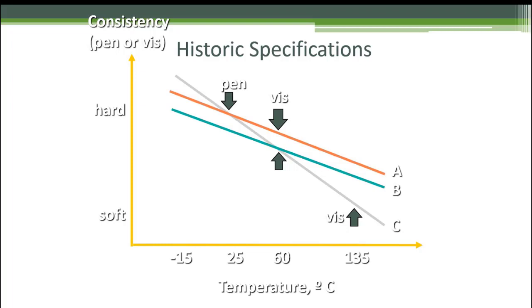But same traffic, same roadway, what happens to those 2 asphalts as they get those extremely cold winter temperatures? C is going to crack quicker, right? Because its cold temperature properties are much more brittle. A is much softer, even though they grade and spec the same for pen grade. So you can build the same road, same spec, same thickness, everything the same, and everything meets specification. But I'm sure hoping that I got an A asphalt and not a C asphalt from this chart when I get to cold temperature cracking.